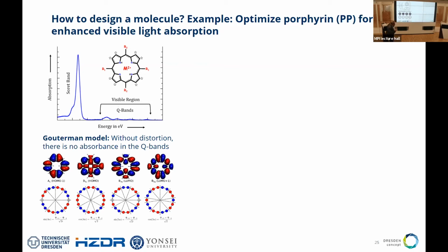And there's a very simple theory about that, the so-called Gouterman model, which basically says in a porphyrin, you have 18 electrons that are on a circle. And if you calculate everything, then you get a very strong absorption, which we are calling the Soret band. And that absorbs in the ultraviolet, so it's not too useful. And if you distort the perfect ring of 18 electrons, then you get additional absorption, the so-called Q bands. They are in the visible region. So that's what we would like to have.